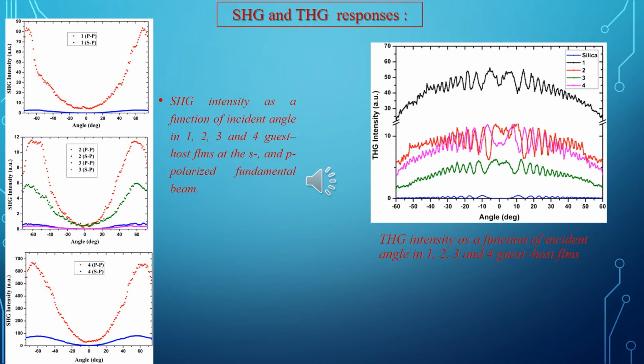second harmonic generation and third harmonic generation of product 1, 2, 3, and 4 in PMMA films at the concentration of 100 micromole per gram were obtained by using the Maker fringe technique for S and P polarized fundamental beam. The film of complex 4 was found to exhibit higher second-order optical nonlinearity than the 3 other films. This result might be due to different polarity and hence different charge transfer from the metal to the pi-conjugated acetylide azobenzene system MLCT in complex 4 as compared with the other three ruthenium metal complexes.